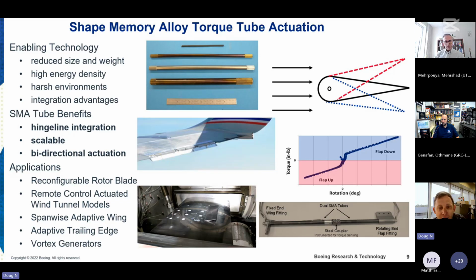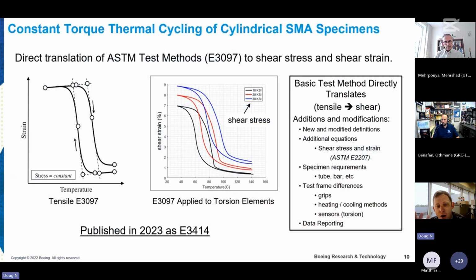It's a highly valuable mode of actuation that we could take advantage of with shape memory alloys, but it also doesn't have any standards. So the third test method we published is constant torque thermal cycling of cylindrical shape memory alloy specimens. And here it's essentially a direct translation of E3097, the constant force thermal cycling test method, except we're looking at shear strain instead of strain. So shear strain, temperature space.